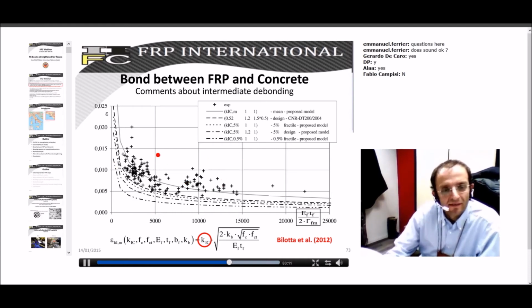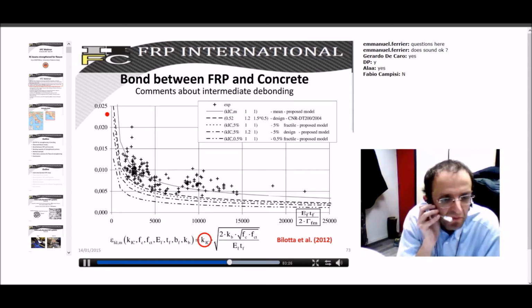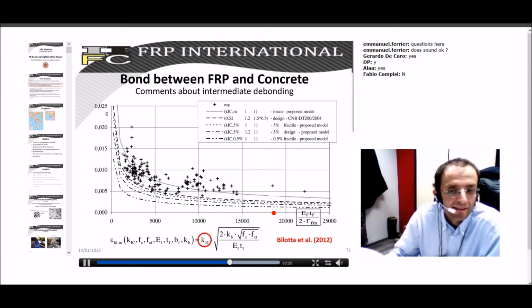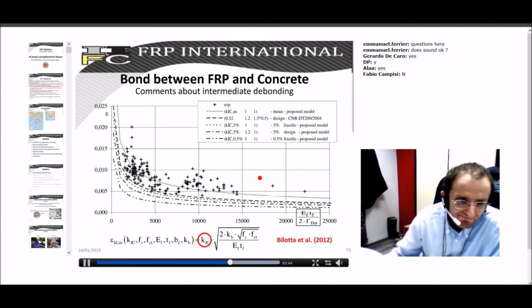Somebody took some experimental results from literature and realized that there is a certain correlation between the epsilon, the maximum mobilized epsilon, the maximum mobilized axial stress at the intermediate debonding, and basically the axial stiffness of the glued strip divided by the fracture energy of the interface. And then this kind of formulae were proposed, both in ACI 440 or other codes.